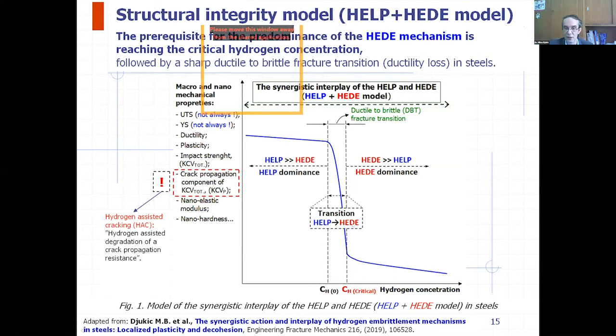lower hydrogen concentration to HEDE dominance, and also a very sharp drop of some micro and nanomechanical properties. The most affected properties are ductility, plasticity, and also crack propagation resistance, which we investigate as the crack propagation component of impact strength during the Charpy testing, which shows a sharp drop upon the reaching of critical hydrogen concentration. And also we have a very sharp ductile to brittle fracture transition due to the reaching of critical hydrogen concentration. So failure occurs after the degradation of micro and nanomechanical properties.